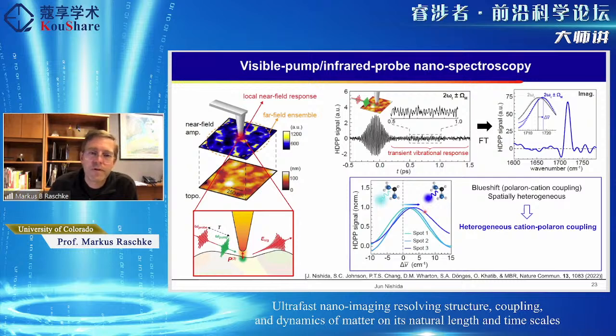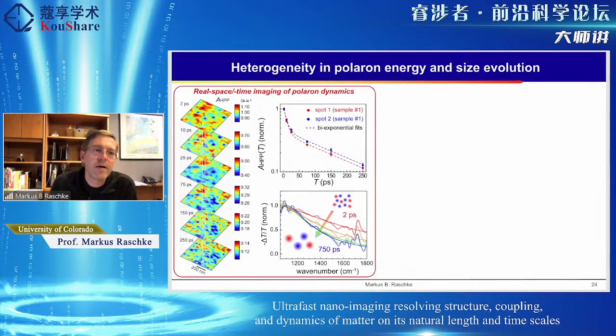But also when we probe at different positions on the sample, we see a varying degree of this blue shift. And so we can hypothesize about this heterogeneity, again, associated with differences in local chemical and structural characteristics of the sample. So this, of course, prompts the question, can we monitor this polaron dynamics in real time? And this evolution of these polarons, and so now if we would really do a full evolution of this spatiospectral and temporal dynamics, then we could learn something about the polarons. And so what you see here now is probing in the mid-infrared the pump-induced response as a function of time delay.